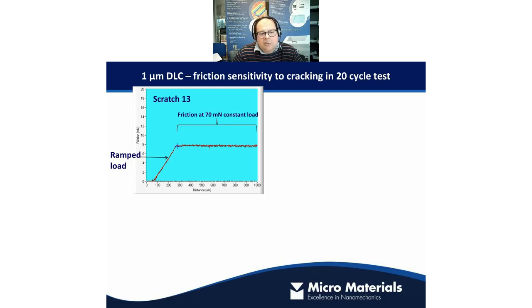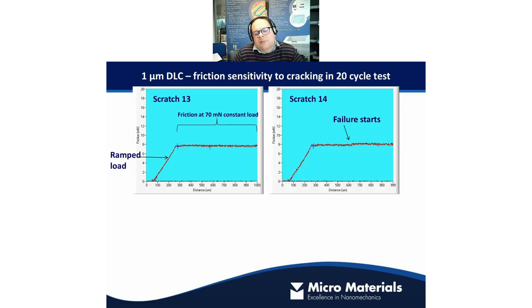We don't want to shock load the sample, so we ramp the load up. The period of the test that I'm interested in is when I reach my 70 millinewtons maximum load. So here we're joining the event at the 13th repeat scratch of 20. And what we see is a pretty stable frictional force acting on the probe at about 8 millinewtons. When we then look at scratch 14, we see a small step in friction. So maybe there's an additional, potentially quarter of a millinewton force acting on the probe there. That could be something or nothing at this point, but let's go to scratch 15.